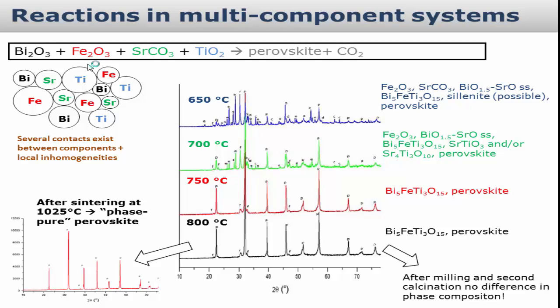Having a homogeneous mixture of 4 components is not good. This is simply because you have all possible contacts inside the powder between, I don't know, bismuth and strontium, bismuth and iron, all 3, for example. And that creates sites at which certain intermediate phases, either binary ones, for example bismuth-strontium, bismuth-iron, and so on, can be formed. And this is experimentally exactly what we observed.